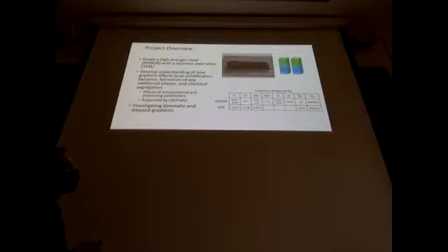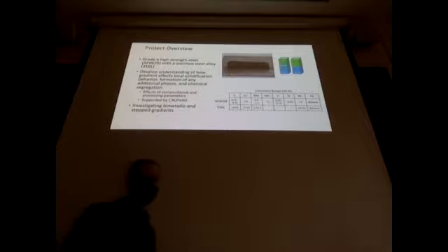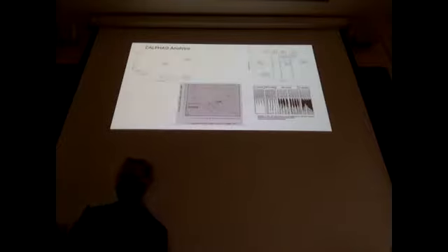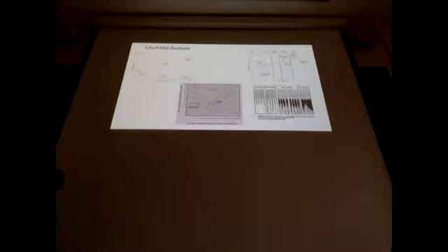There's chromium, moly, manganese, silicon as well, nickel. So all these things play into the strength of that alloy, and we're doing it to 316. And so we're keeping a lot of these constituents there. The only thing that we're possibly doing is removing that carbon. But overall, this is why we chose this alloy, because it looks like it should be a fairly simple alloy to make, and we shouldn't have any problems or issues that come up.